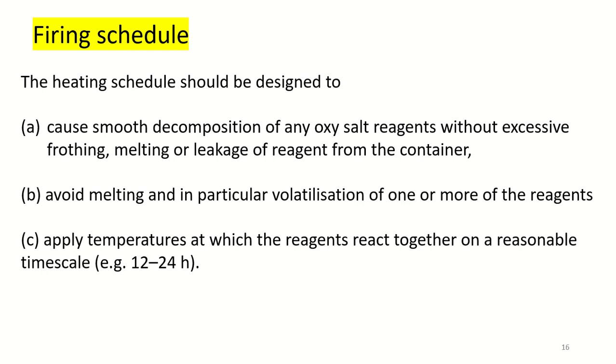B, it should avoid melting, and in particular volatilization of one or more of the reagents. And C, apply temperatures at which reagents react together on a reasonable time scale. The reasonable time scale should vary from 12 to 24 hours.